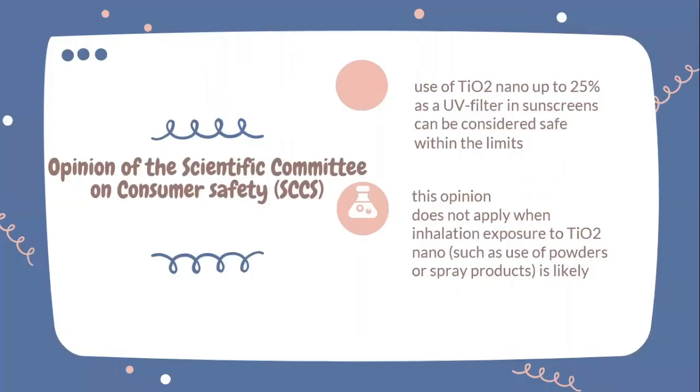Okay, next. Opinion of the Scientific Committee on Consumer Safety, which is SCCS. The safety assessment has shown that the use of pigmentary titanium oxide in loose powder up to a maximum concentration of 25% in a typical face makeup application is safe for the general consumer. It needs to be noted that these conclusions are based on the safety assessment of titanium oxide in the context of possible classification as a category 2 carcinogen.